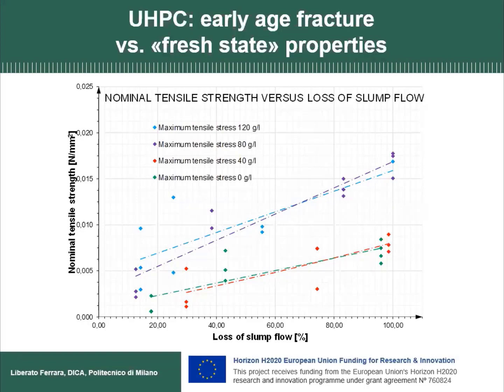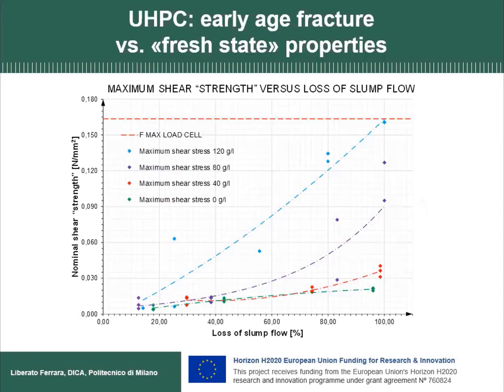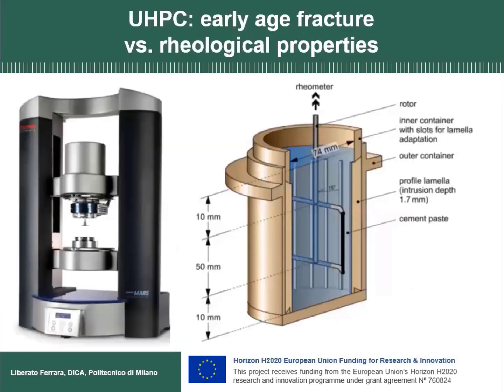What is interesting is that we tried, as a first attempt, to correlate the tensile strength of the fiber reinforced composites versus the loss of slump flow. And you can see here that there is a common trend between 0 and 40 kg per cubic meter of fibers, and there is a significant jump when you go to 80 and 120. This was even more evident for the shear stress, where the results for the reference mix and the mix with 40 kilos per cubic meter of fibers are pretty much the same, whereas you have an increase for 80 kilos and a further increase for 120 kilos.